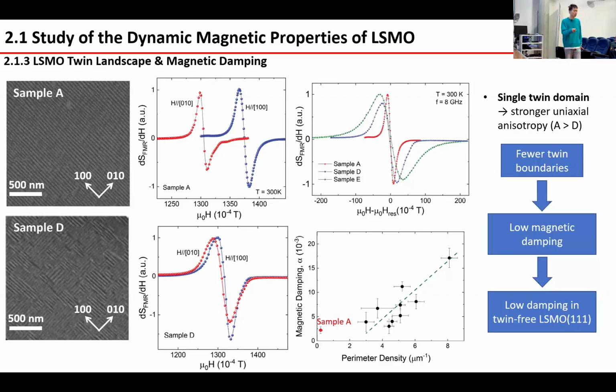Okay. We use the image software. For example, in sample D, we can check by eye that there's a twin, how to say, there are two orientations of the boundaries. We can plot the twin boundaries manually in this figure, calculate the total boundary length, and divide by the area of the image, and then we get the perimeter density. This reflects the twin boundary network density, and it's quite relevant to our work because of the dynamic property and so on. So it arises from the boundary densities. So thank you.